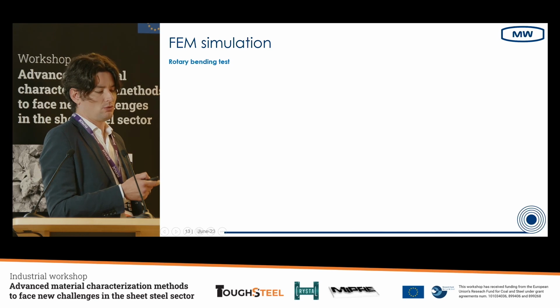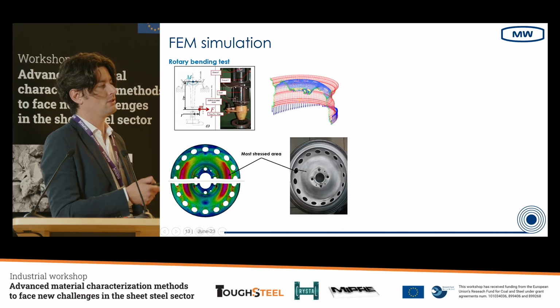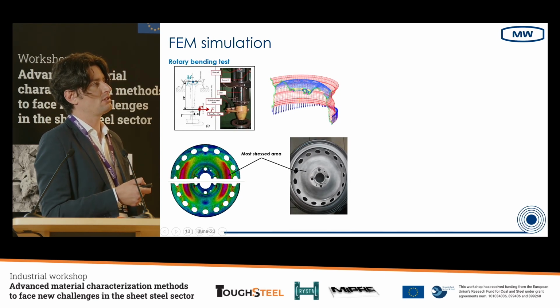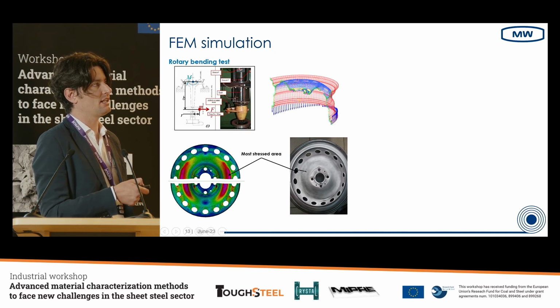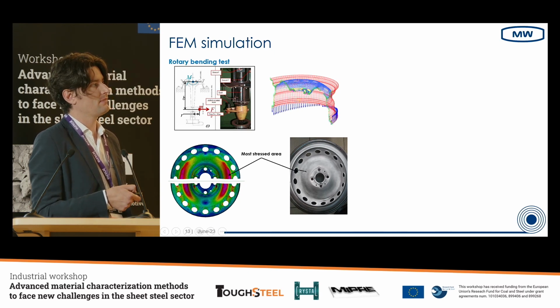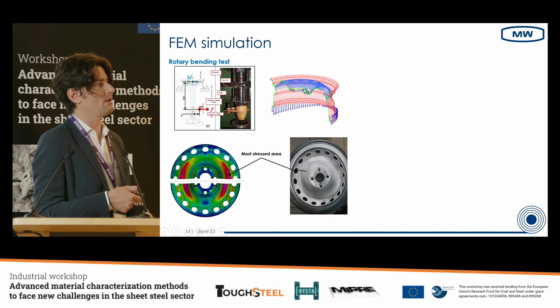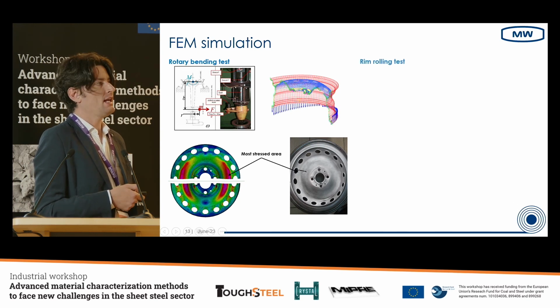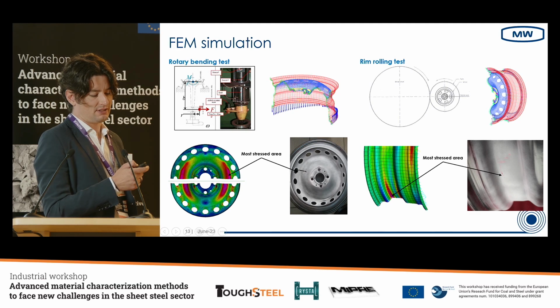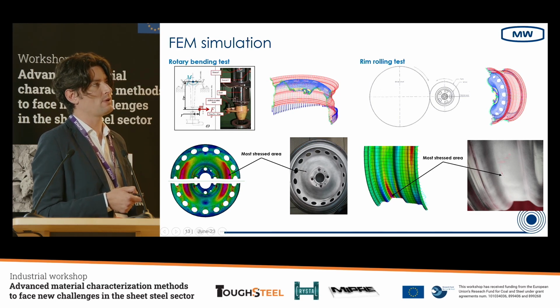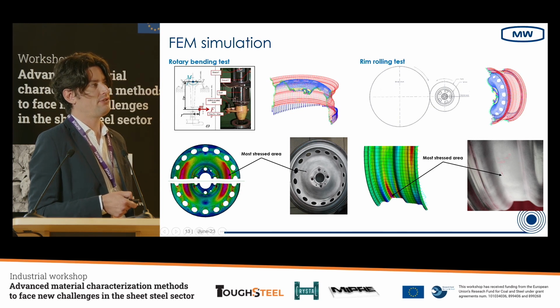So just to show very fast how the rotary bending test correlation looks. As you can see here, in a typical simulation the stressed area corresponds exactly to where we have the crack. The same for the rim rolling test simulation, in which we apply the loads, the distribution of the loads, and so on. And the FEM detects that the critical area is this, and in fact the crack is here.